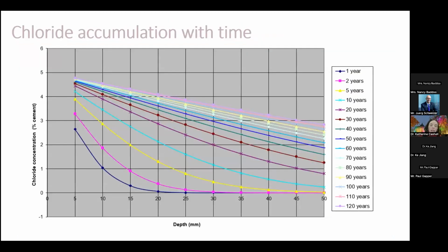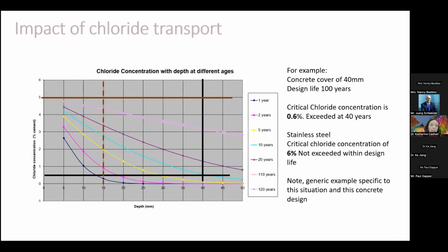Briefly on the chloride accumulation, this graph shows the accumulation of chlorides in concrete with depth and over time. And if we look at the next slide, which is an application of that same graph, this is a very simple example. If we take a structure where the concrete cover is 40 millimeters and a design life of 100 years, the critical chloride concentration for carbon steel rebar is 0.6%. We can see down at the bottom, these solid black lines, at 40 years, that 0.6% has been very much exceeded by carbon steel reinforcement.